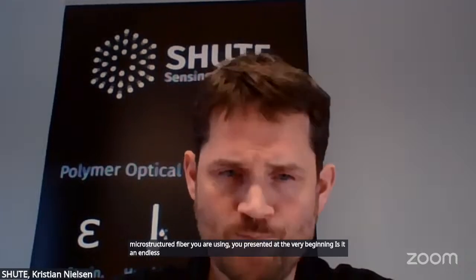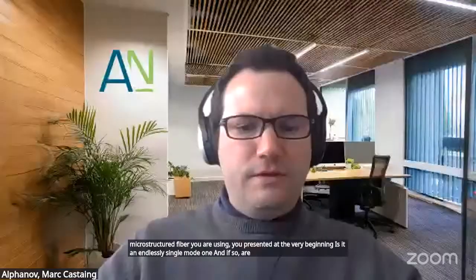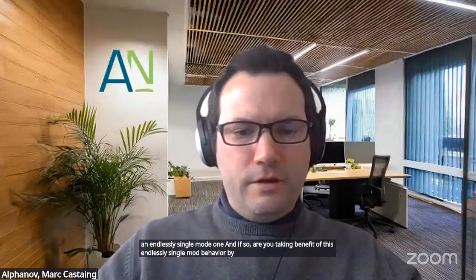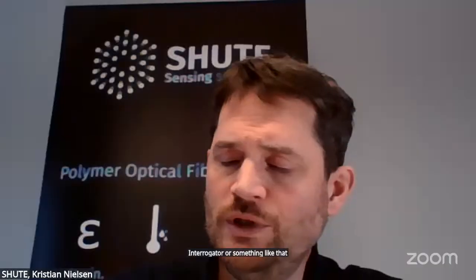Okay, yeah, understood. So Mark, please. Yes, thank you. Very nice presentation, Christian. I was wondering, the microstructured fiber you presented at the very beginning, is it an endlessly single mode one? And if so, are you taking benefit of this endlessly single mode behavior by having a broadband interrogator or something like that? Yeah, we manufacture our fibers to be endlessly single mode. That means that we can address the C-band and the 850 nanometers in the visible range with the same fiber, basically. The limiting aspect for us seems to be the optical components available. So we normally operate around 800 to 850 nanometers, mostly because that's where we can find most of the components that we need. But as you point out, we could use the fiber for the whole range from 400 to 1500. Okay, great. Thank you very much.